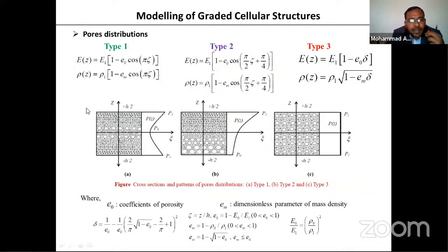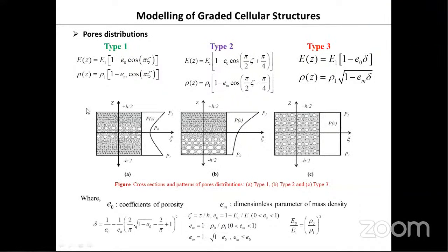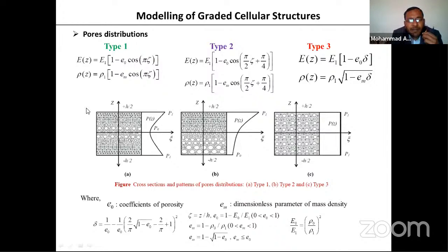Then in the case of type 1 distribution, the effective material properties are minimum at the center because it has maximum porosity at the center. And for type 2, the maximum porosity occurs at the bottom surface, so the effective material properties vary accordingly. In the third case, it's a uniform distribution, meaning the pores are uniformly distributed throughout the structure, so the effective material properties have nearly constant values.